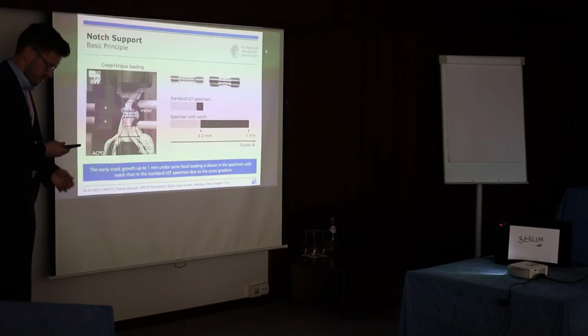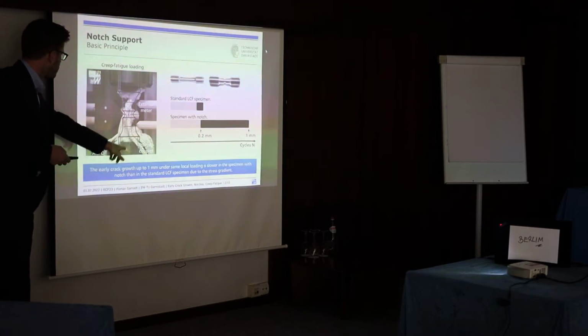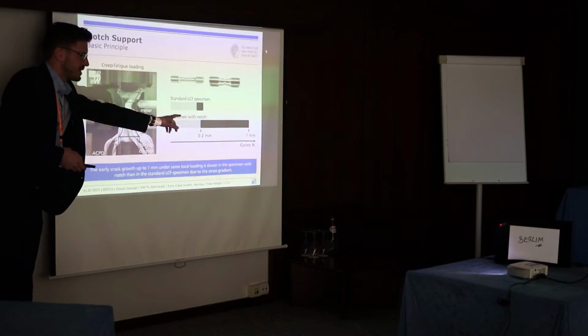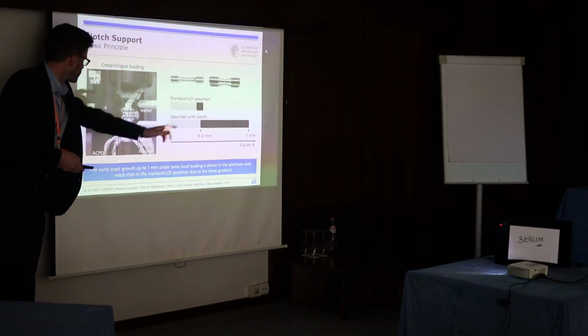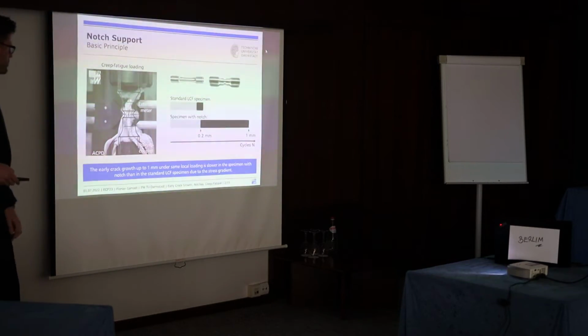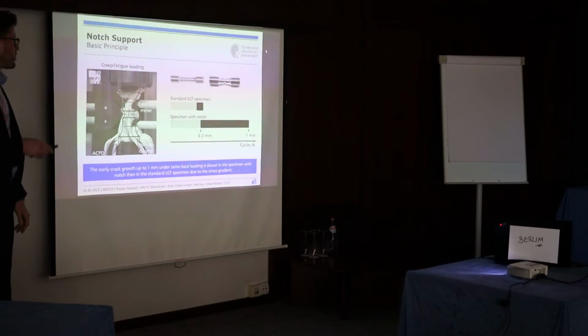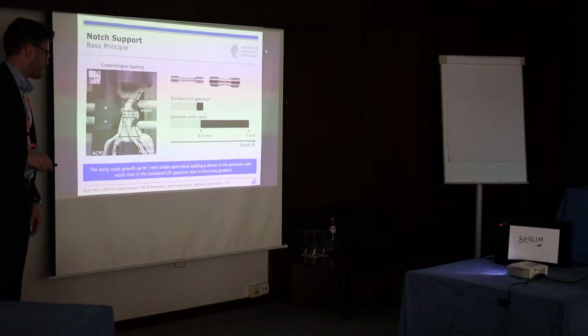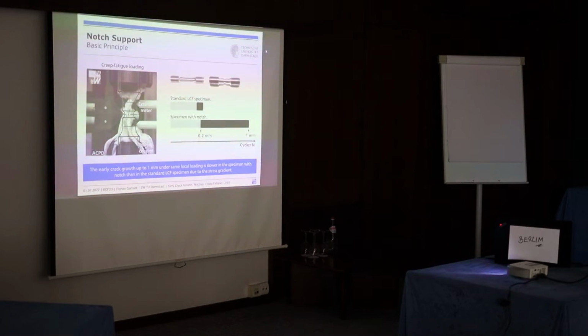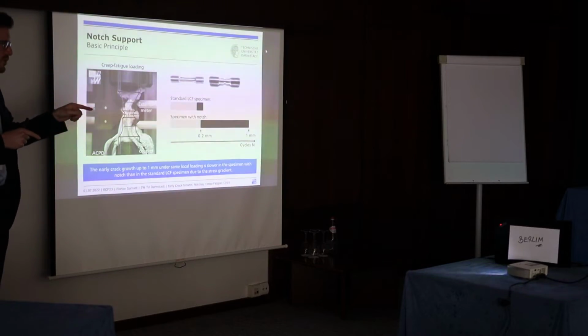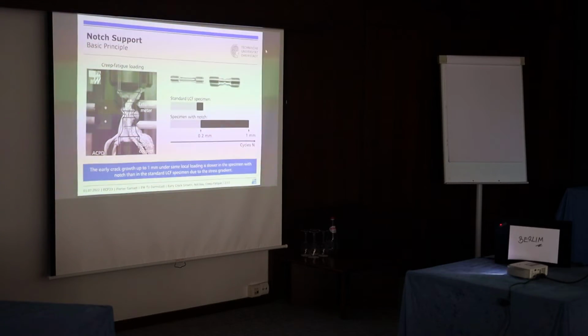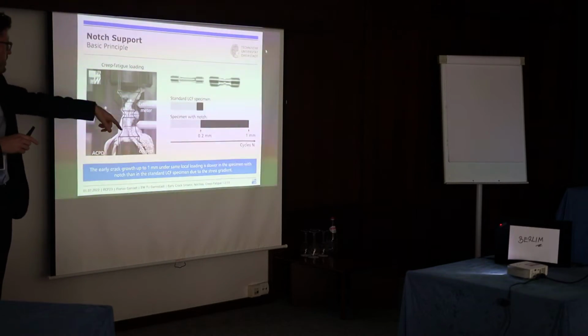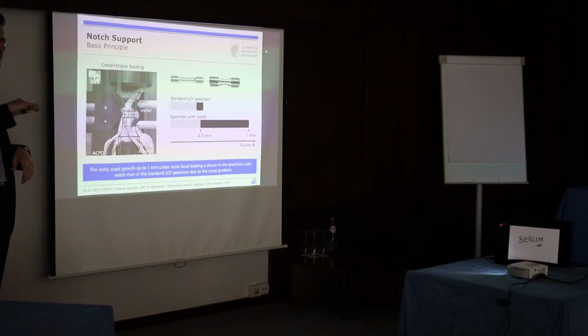The temperature is controlled by thermocouples. You can see here in the LCF regime, we typically do strain control tests, so we need an extensometer to control the displacement. And we measure this crack growth by using an alternating current potential drop technique. One important thing I already mentioned is that we are looking for the same crack depths, and the second important thing is that we do this comparison of cycle numbers at the same local loading level. This is really important here.